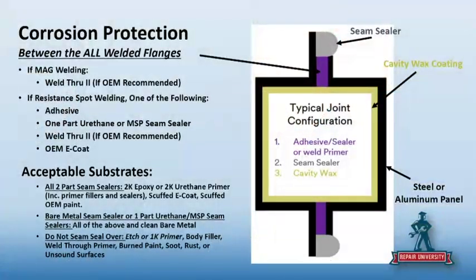Then for bare metal seam sealer, you can go over all of the above, the same things I mentioned. You can put a bare metal seam sealer over primers and E-coats as well, and also over bare metal. But here's where you do not want to apply seam sealer: over an etch primer, a 1K rattle can type primer, body filler, weld-through primer, burnt paint, soot, rust, or unsound surfaces. That sounds funny, but I see it all the time, where you see soot from the welds and a seam sealer right over the top.